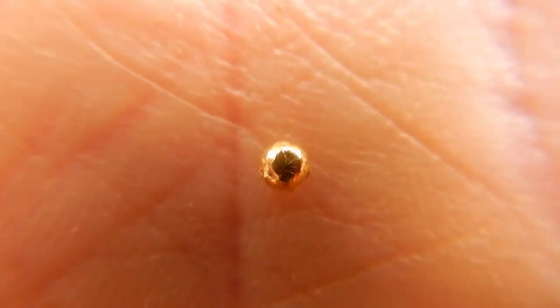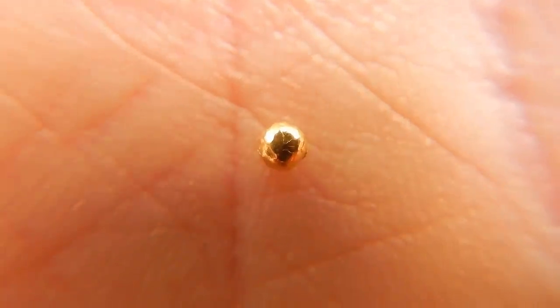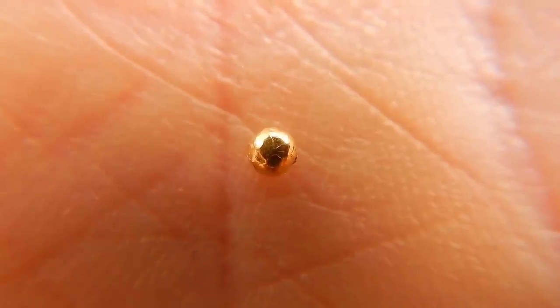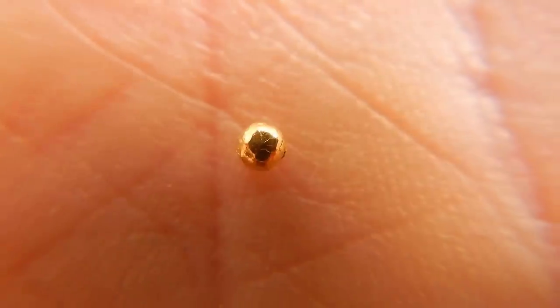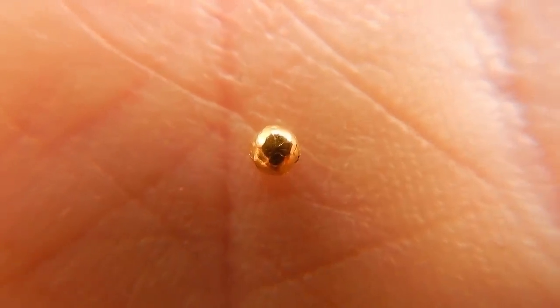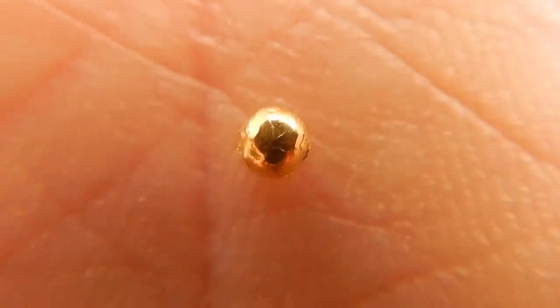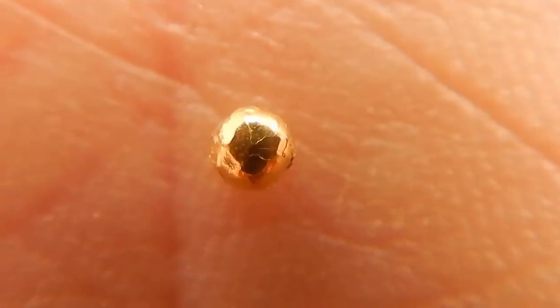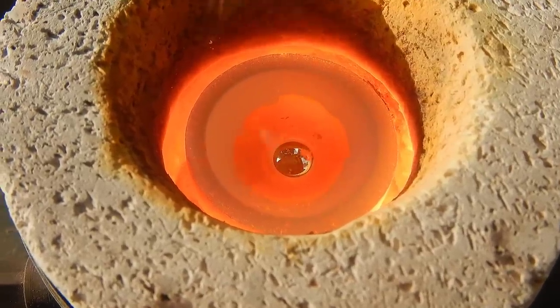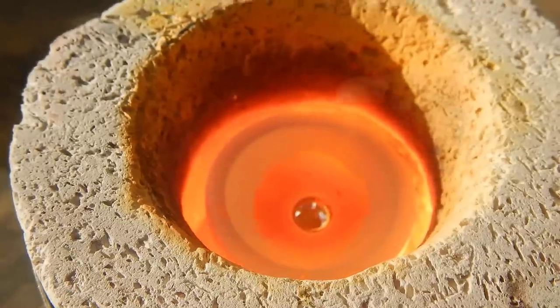Well, it's a pretty little ball of gold, that's for sure. But it's not the five grams I was hoping for. That material that sort of fooled us — what it was — was definitely just lead with an iron oxide staining making it yellow. That little ball of gold would have been that little piece of gold that I saw in there, and maybe a few little remnants squished into the lead or something. But that's not even point one gram. Definitely not the five grams I was hoping for.